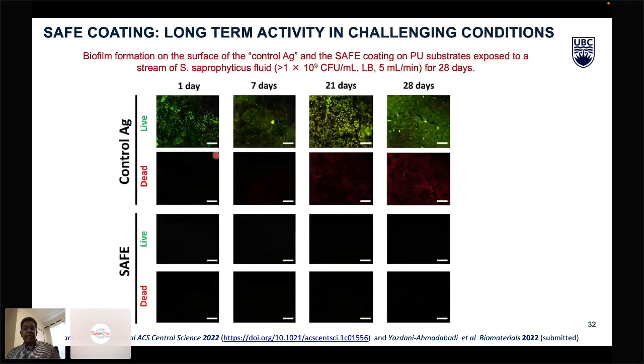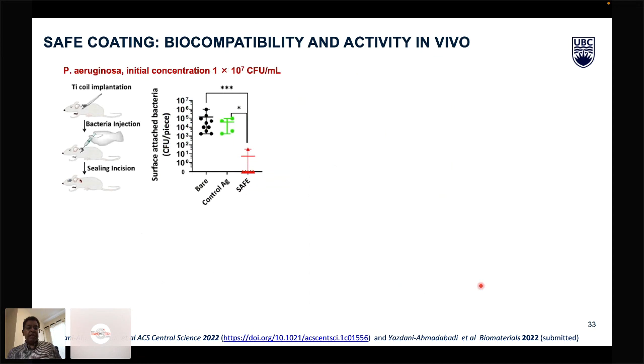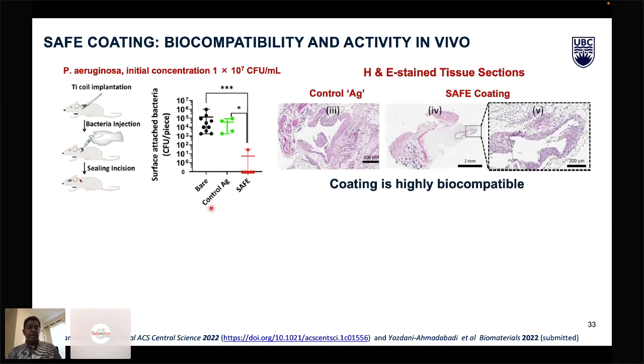And we have seen that in challenging conditions too. And this safe coating is remarkable in preventing the adhesion. And here again, the controlled silver coating, by 28 days, you could see a lot of biofilm formation. And as I mentioned earlier, this is due to the fact that dead bacteria get adhered to the surface, and on that the bacteria colonization is happening. But these anti-adhesive properties in combination with the silver are able to prevent the adhesion of bacteria. And we looked further in an implantation model to look at its activity.